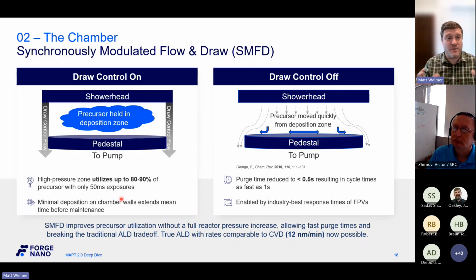So we don't have to worry as much about particle generation from the chamber walls, which is a good thing for maintenance time and that sort of thing. When we talk about purges, this allows us to reduce our half cycle purge down below half a second, again, depending on the process. So that means we're switching from high to low pressure within each half cycle, right? So we have to do this twice each cycle. So really it relies on those FPVs.